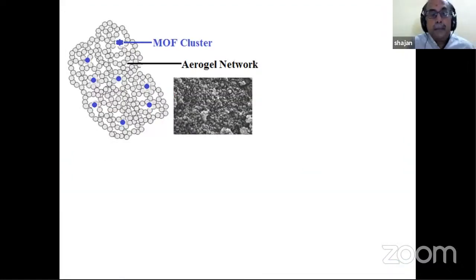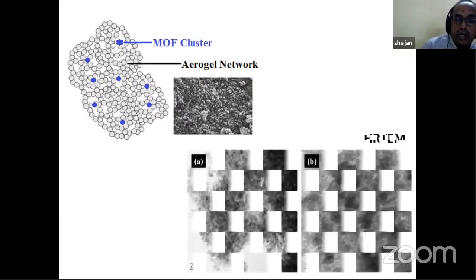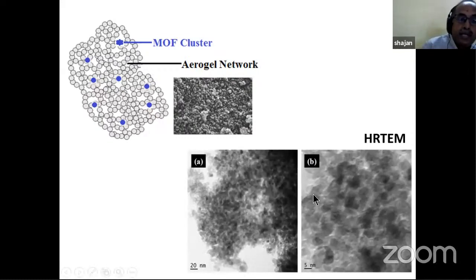Now this is the image, and you can see the detailed HRTEM image. You can get a very good idea. Now this is the structure that we have proposed, and these are the aerogels, and the blue color is the MOF, because we have added a very small quantity. These blue colors we are seeing here are the MOF clusters, and you can see that is being reflected in the HRTEM image. The dark black portions are the MOFs that we have added to the structure.